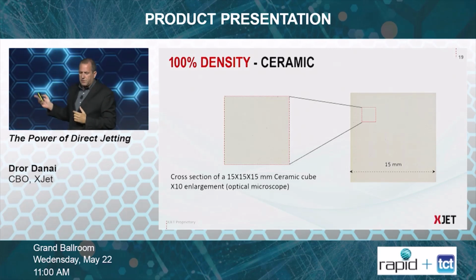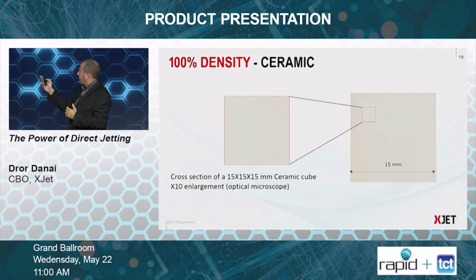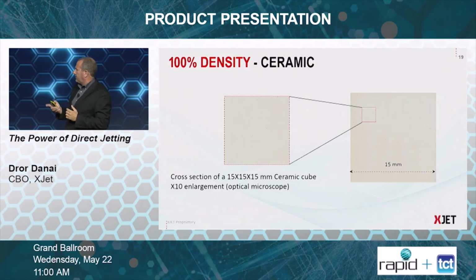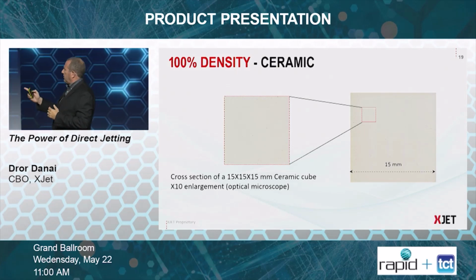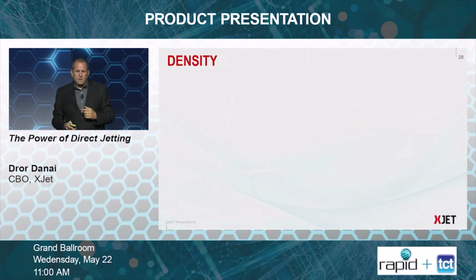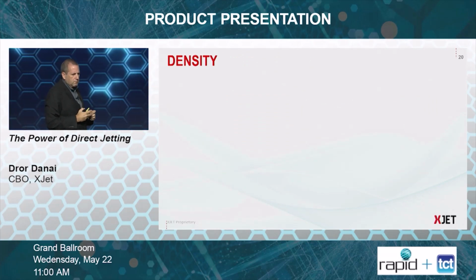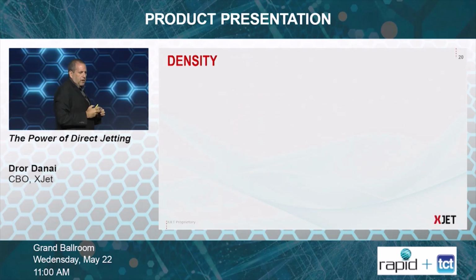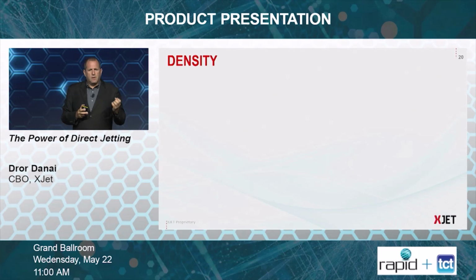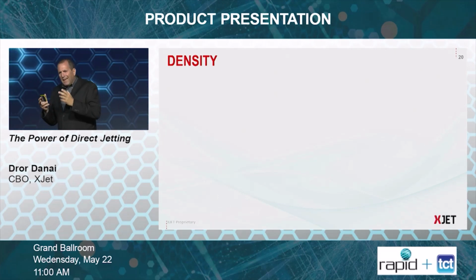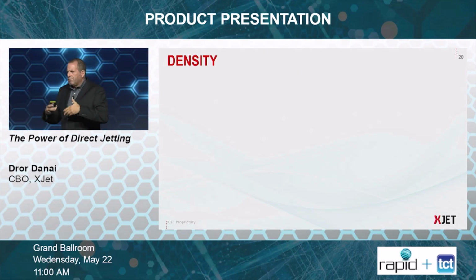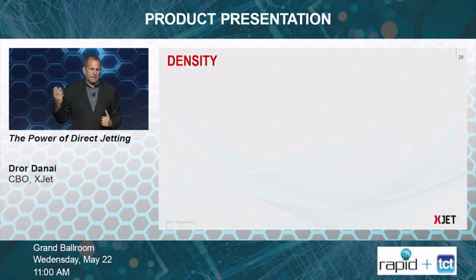If you look at this cross-section, this is a 15 by 15 by 15 millimeter ceramic cube, enlarged, and you can see no porosity and very close to 100% density, that allows the creation of the 5G antenna that I mentioned in the beginning.